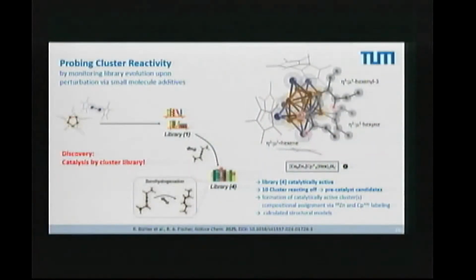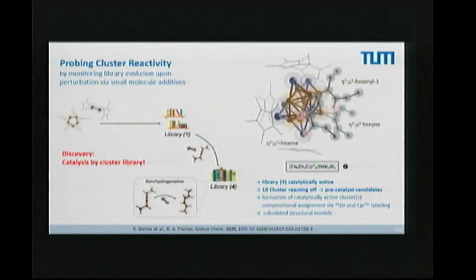And if we analyze our abundance of species in the library, we find a new one. The new one has a copper 9, zinc 7, 6 Cp stars, 3 C6 units, so 3 hex units, and 3 hydrogen atoms. And the calculation framework reads out something like that, where we have a complex copper zinc cluster, and one phase, you will see in a minute more in a better image, and one phase is capped with various forms of hexyne molecules having 2 hydrogens, 1 hydrogen, or being a hexyne molecule just attached to the cluster surface.